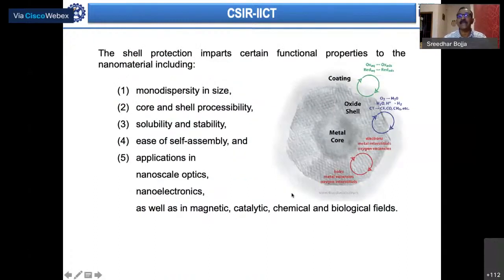Now, when you have this kind of metal core, and you're talking about an oxide material or a metal as a nanoparticle, there is every possibility that the surface gets oxidized depending on the atmosphere in which it is placed. So even then, it is a core shell nanoparticle, with metal as the core and oxide material surrounding it. And it is this surface which is responsible for all the catalytic activity, like oxidation or reduction reactions, or any other modifications.